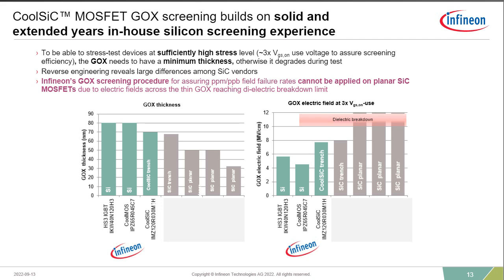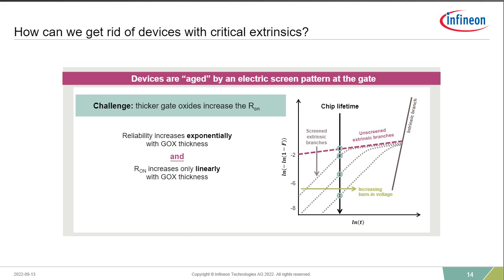You can see on the right that once those devices are driven at the recommended gate drive voltage, the dielectric field on them is quite high. This prevents these devices from being driven hard to filter out the dielectric or extrinsic defects in the device. So again, with this curve, the higher the voltage you drive onto the gate of the device, the further to the right you move on the curve: a more reliable product with fewer defects, or a lower failure rate. The gate oxide thickness essentially gives an exponential improvement in the long-term reliability of the device, while only providing a small linear reduction in RDS(on) per chip area with respect to gate oxide thickness.